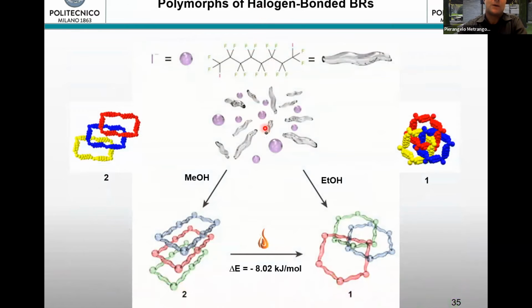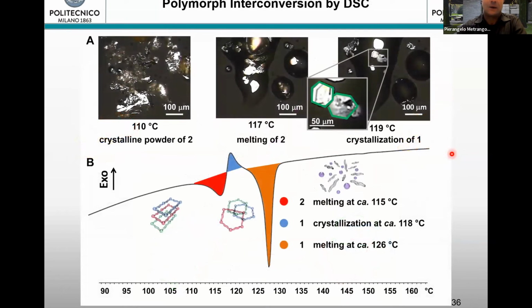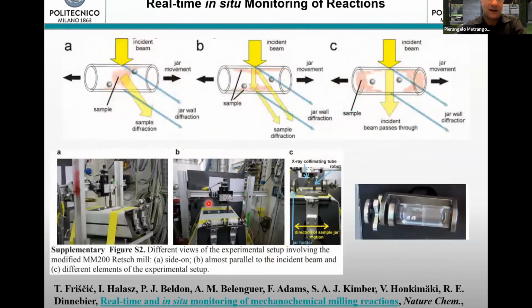Moreover, we were looking at whether we could also isolate the non-interpenetrated polymorph, and actually we were able to do that by simply changing the crystallization conditions from ethanol to methanol. We always get the same honeycomb-like structures, which were interpenetrated only in the case of the ethanol co-crystal. And we could characterize that these two are polymorphs, where the non-interpenetrated system converts upon melting into the Borromean interpenetrated system.